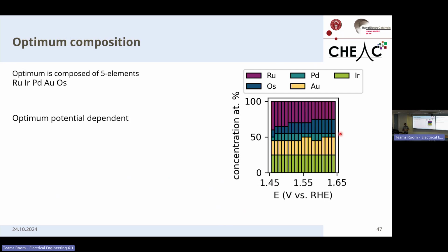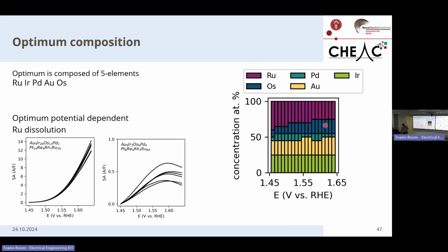And here we see two things. The first thing is that the optimal composition is always a 5-element arrangement. The other thing that we can see is that the optimum composition is potential dependent. The more you go up in potential, the less ruthenium you have in your system and the more osmium you get in return. So the reason why we have a change in optimal composition has to do with the stability of ruthenium in acidic environments.